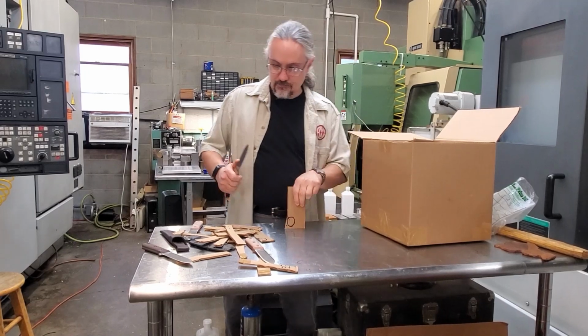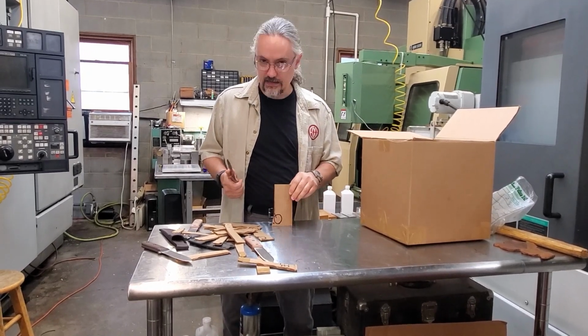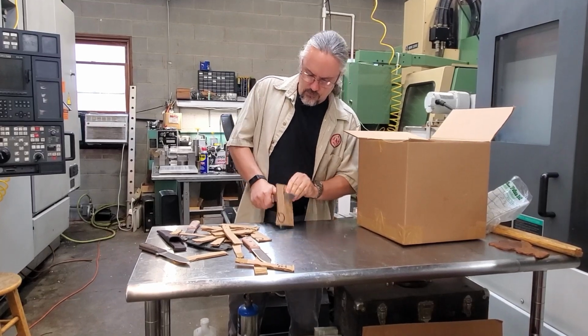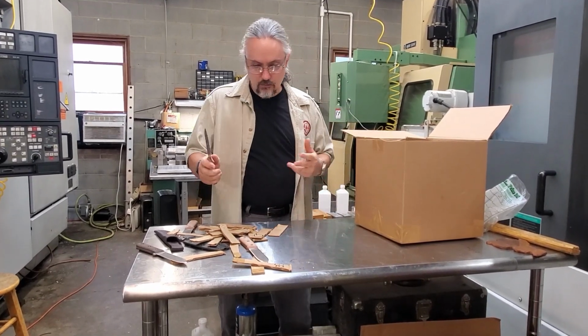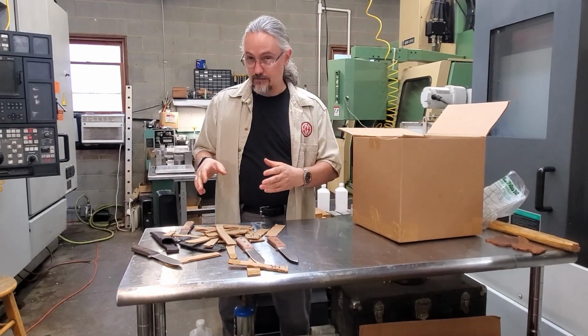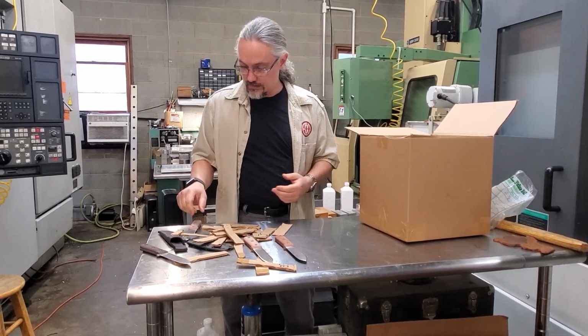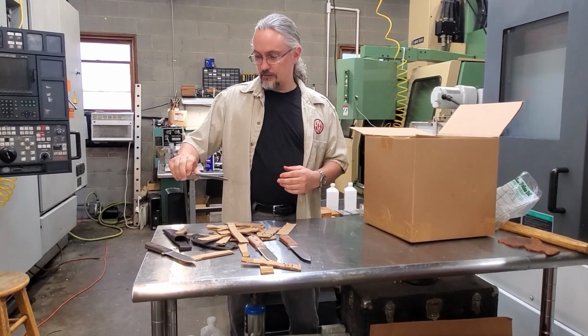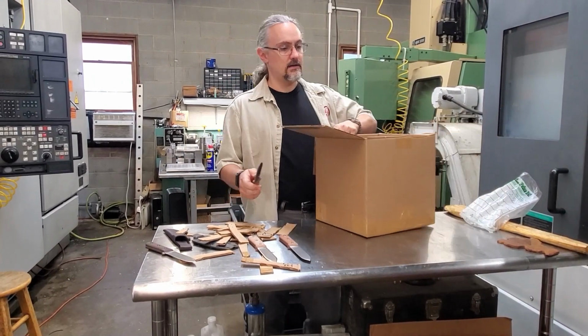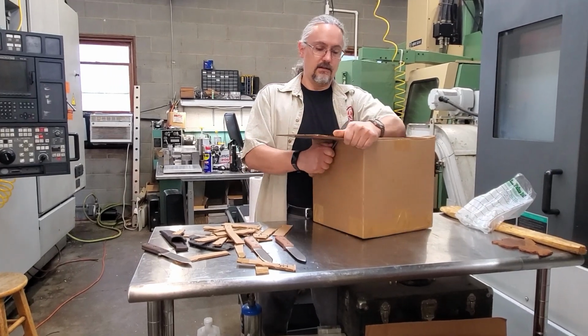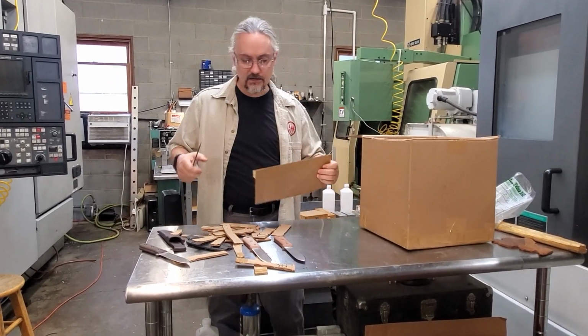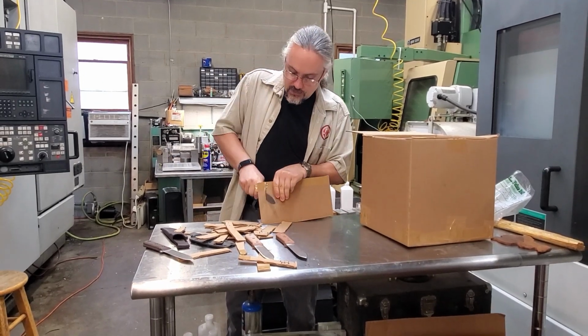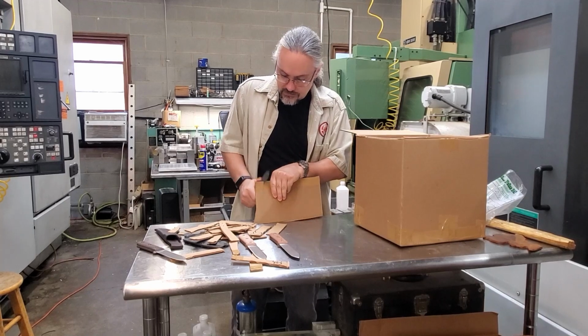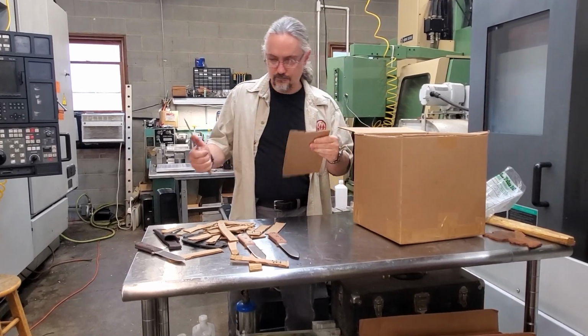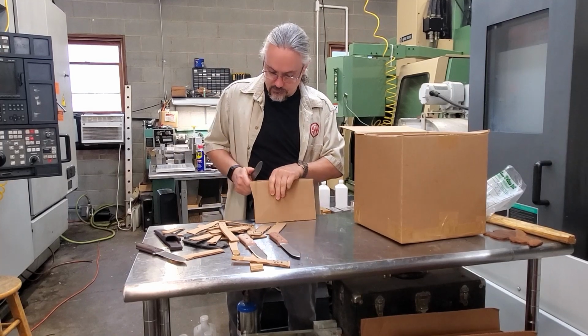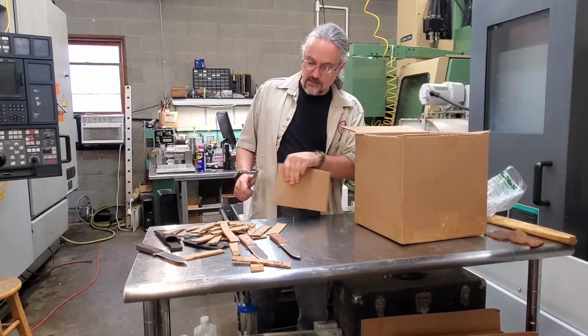One is they're intended to stabilize a little bit of retained austenite. I won't go into a lot of detail on what that is and what it does, but for a knife, it's not good to have in your knife edge because it's soft, but it does reduce part growth. The other thing they'll do is design the steel so that it gets hard at the secondary hardening hump. So you can get this steel pretty hot, and there's a lot of advantage to being able to get steel hot in use. There are tons of reasons why you would want a particular tool to tolerate heat.